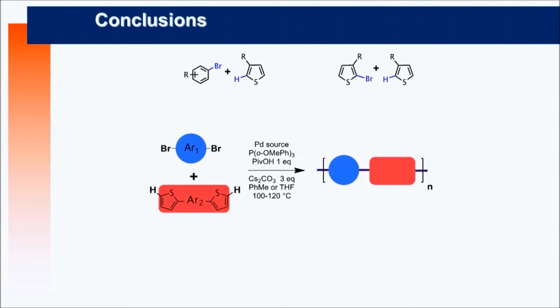In conclusion, these are our general conditions to slow down and have a better control of the polymerization reaction. It's not the best condition to make a quick reaction for small molecules. It's really typical for conjugated polymers. So we need a palladium source. Palladium acetate is good. This is a ligand developed by Ozawa. We like it. We need pivalic acid developed by Fagnou. Cesium carbonate, 3 equivalents. We prefer toluene and THF. Toluene and THF is good.